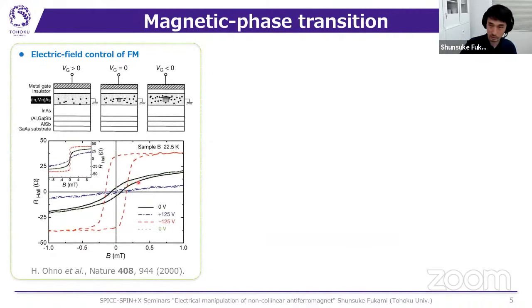Okay, and the next phenomenon is the magnetic phase transition. In 2000, Hideo Ohno and his colleagues demonstrated that the electric field can induce the phase transition of ferromagnetism. They used magnetic semiconductors, and these material systems exhibit ferromagnetism that originates from the holes. So by tuning the concentration of the holes, they can control the ferromagnetism.